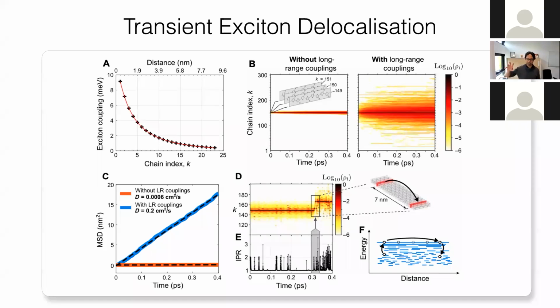So what can happen in organics, and you can see this in just a photoluminescence spectra when you look at the vibrational peaks, and you can see the Huang-Rhys coupling essentially reflected in that. The excitons are very strongly coupled to these vibrational modes. So these vibrational modes essentially provide the exciton energy to jump up in energy for a small amount of time before it is relocalized. So you delocalize it with a vibrational kick, it moves, and it will relocalize.